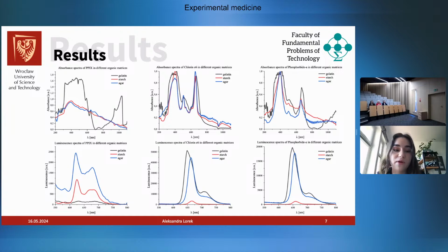A different situation can be observed with matrices doped with chlorin e6 and pheophorbide A. Absorption spectra are similar, but the gelatin peak was wider. Also, the highest luminescence peak, but it's relocated towards lower wavelength. Agar matrices have had the most accurate luminescence and absorbance spectra, also consistent with literature, and have relatively high quantum efficiency, so they are the best for tested photosensitizers.